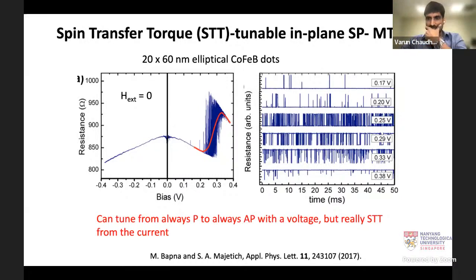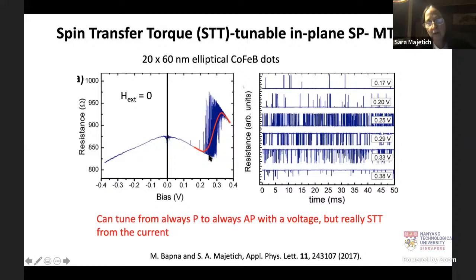So anyway, back to the resistance versus bias voltage. What you find is that here, because these devices are switching so fast, we don't see an open hysteresis loop as we ramp the bias up and then back. What you see is this sort of grass as it's switching back and forth between the two states, the parallel and the anti-parallel.